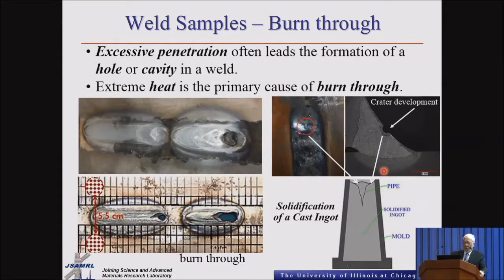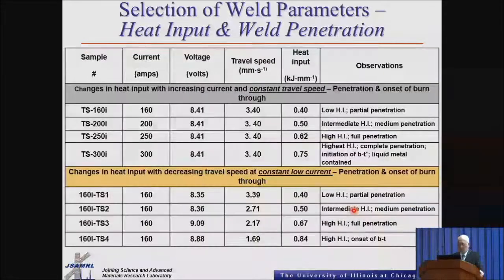Now, one of the things tied up with the burn through is the excessive penetration. You can see here two of our welds showing obvious burn through as a result of a hole being produced. And of course, when we're doing the welds, you come up with some areas in which you might have a crater. The crater is some type of hole being produced there. However, that is more a result of the solidification of a casting, for example an ingot, which we know as pipe. So that has nothing to do with burn through.